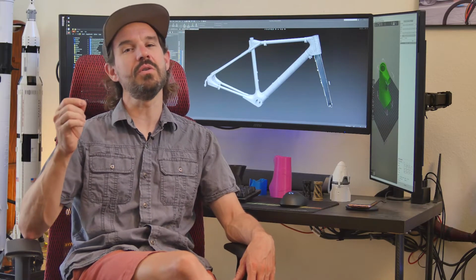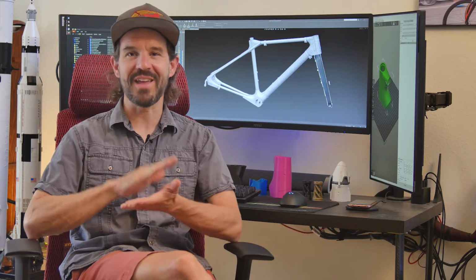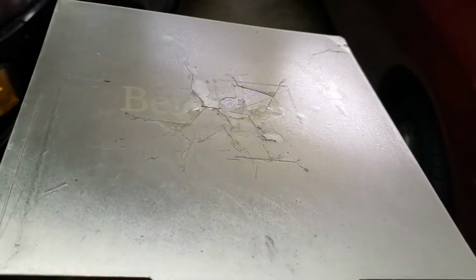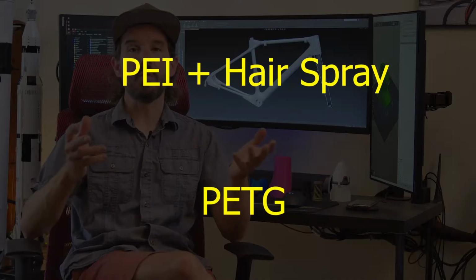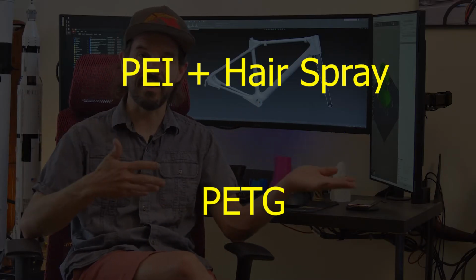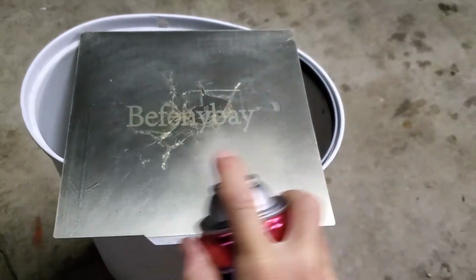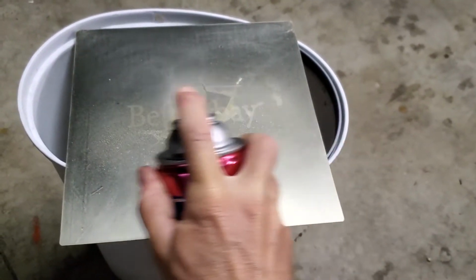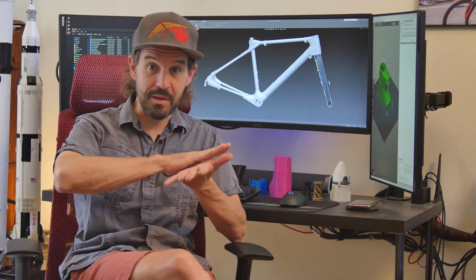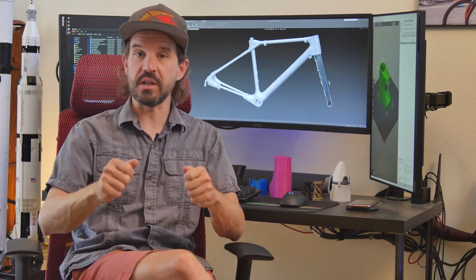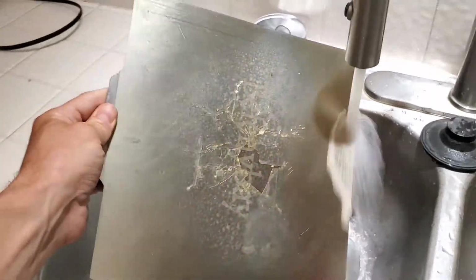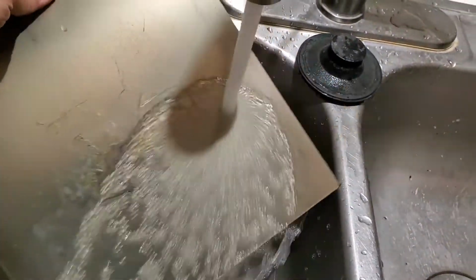Do not use PETG with a bare PEI sheet. The PETG will bond to it and you'll destroy the PEI when you go to remove the part. As a workaround, you can just coat your PEI sheet with hairspray, just like the glass bed, and that works great. The PETG will stick to the hairspray and the hairspray will protect the PEI coating on your bed. And then to remove it, you just flex the sheet like you normally would. And to wash it off, you just use warm water, hairspray washes right off.